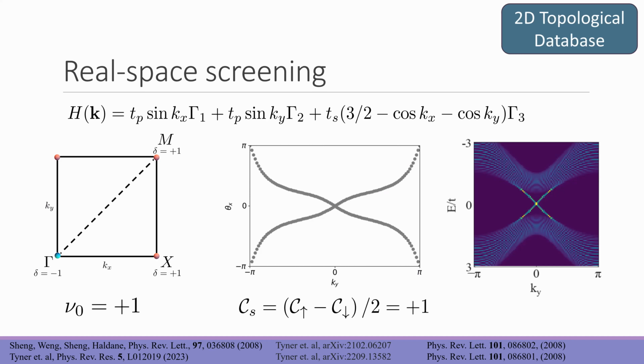We can analyze the non-trivial topology of this model in a number of ways. We can look at inversion eigenvalues and assign a Z2 index. We could also get this Z2 index from the Wannier center charge spectra: we can calculate that, see that it's gapless, and that also tells us about non-trivial topology. We could have looked at surface states, seeing gapless surface states. All these things are in agreement. Furthermore, we can calculate a spin Chern number, shown on the bottom. We have a U(1) spin conservation law here, so we can calculate a spin Chern number and see that it's 1.